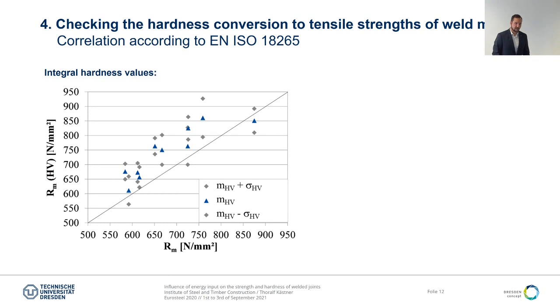But there is a Eurocode, the EN ISO 18265, and this code gives us the opportunity to have a correlation of the hardness value and the tensile strength of the weld. And we examined this. We used the mean values of the integral hardness values, so all hardness values over the cross section were used, and we also take into account the standard deviation of our hardness values.